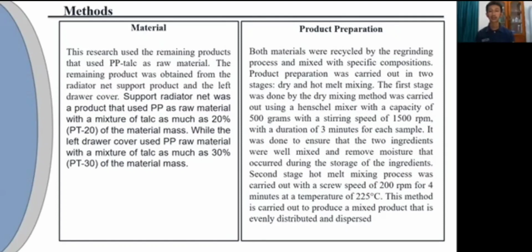Product preparation. Both materials were recycled by the regrinding process and mixed with specific composition. Product preparation was carried out in two steps: one, dry mixing, and two, hot melt mixing. The first step, dry mixing, was carried out using a Henschel mixer with a capacity of 500 grams with a stirring speed of 1500 rpm with a duration of 3 minutes for each sample. It was done to ensure that the two ingredients were well mixed and to remove moisture.